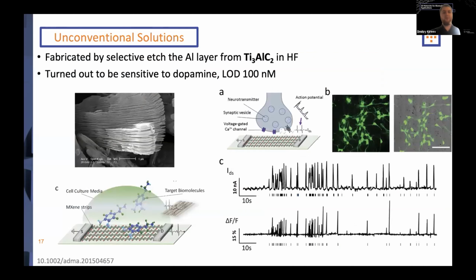Another really interesting and unconventional solution to biosensing, and also neuronal sensing in this case. I just like this work. This is really a manifestation of why 2D materials are so exciting for biosensing. This was a work, I believe, from a few years back, where authors fabricated MXenes, titanium aluminum carbide that was selectively etched in HF. And these devices, just bare devices without any additional modification, turned out to be sensitive to dopamine.